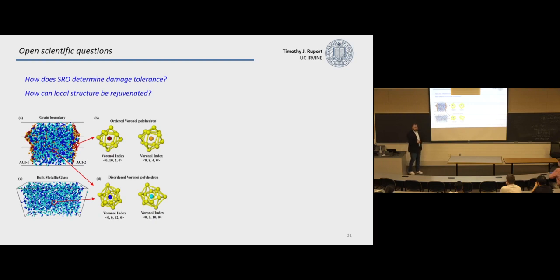And it turns out that that's really important because this is where things like dislocations are coming in and being absorbed, or those point defects from the irradiation need to be accommodated and brought into this bulk material. So we're looking both at these structures, but also how variations in those structures affect the damage tolerance. And I'm not going to show the data, but relatively subtle changes in the density of those ordered packings can give you things like a 2 or 3x increase in the damage tolerance of your grain boundary.